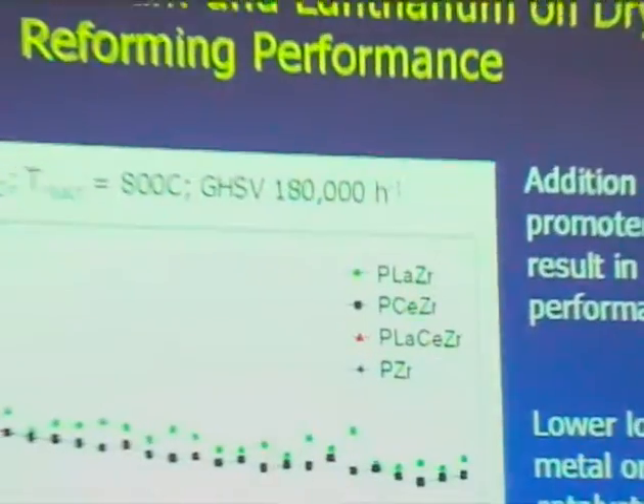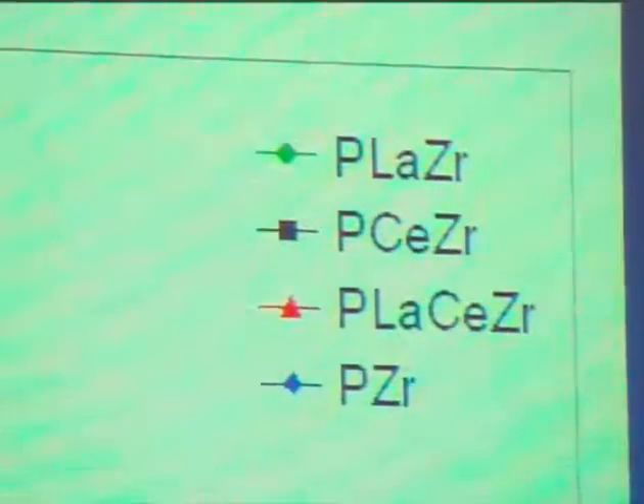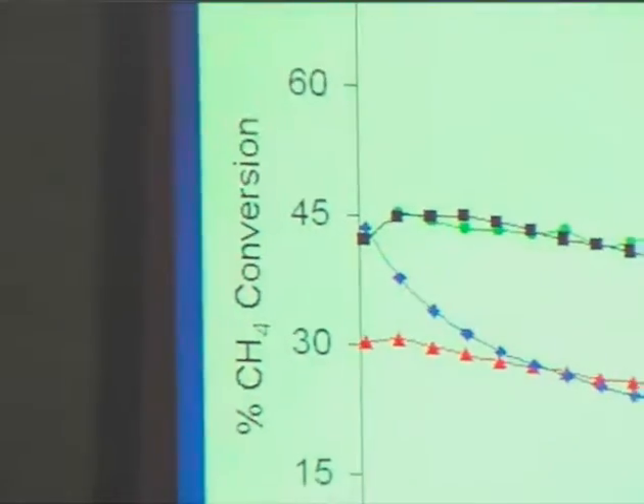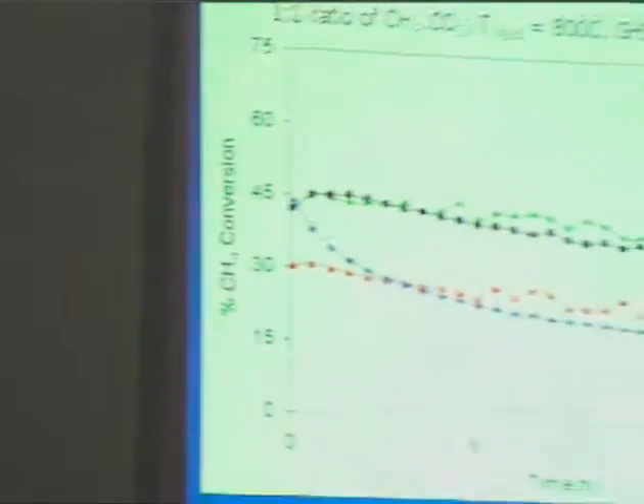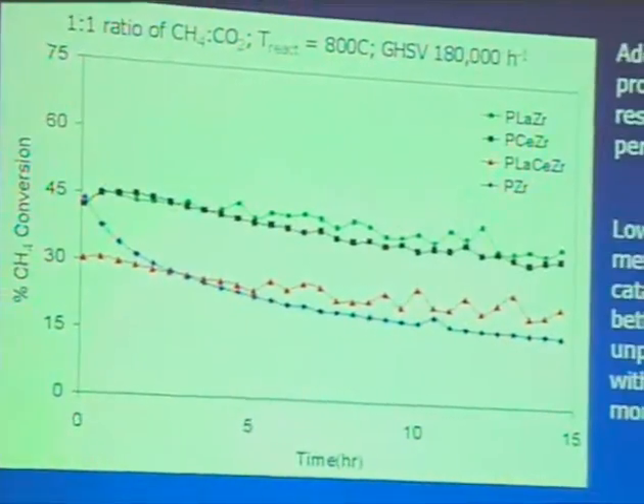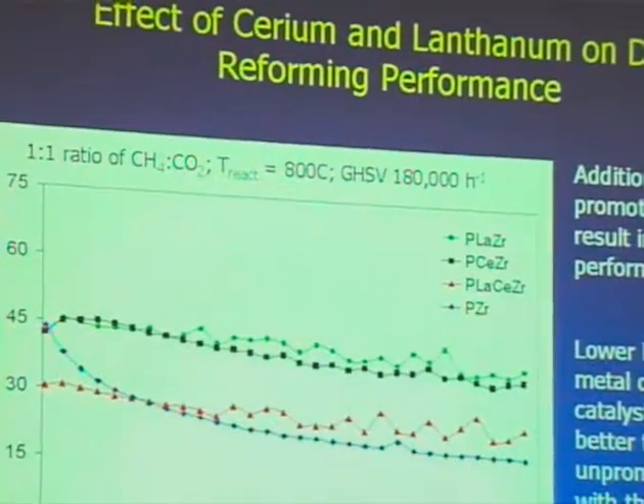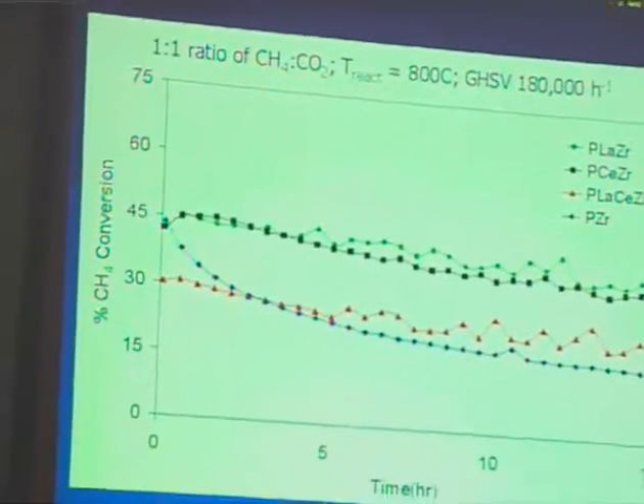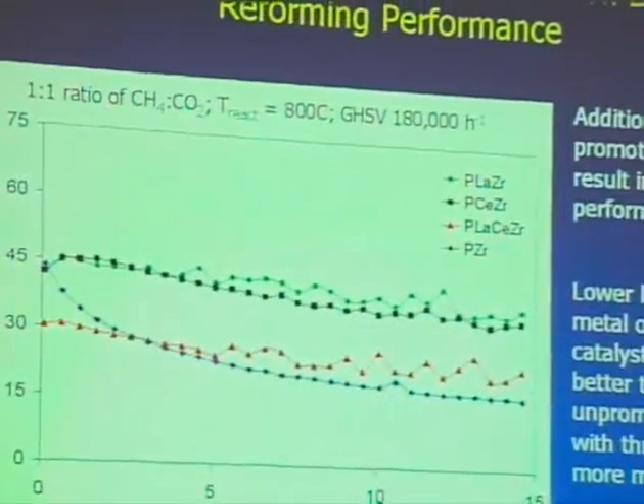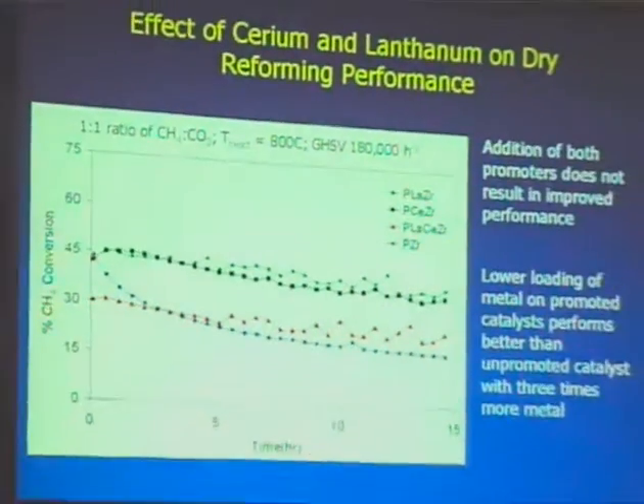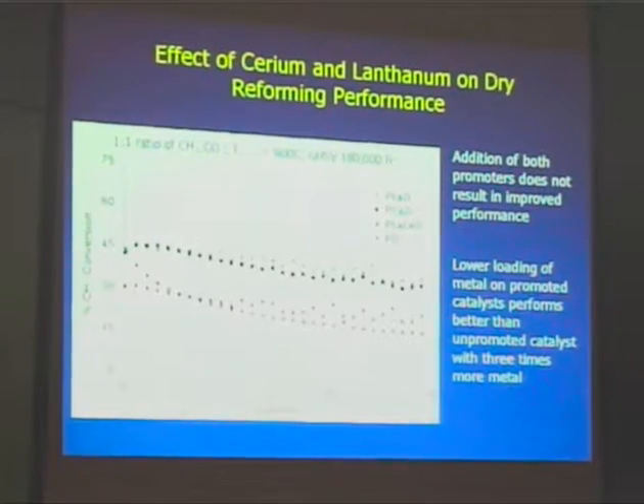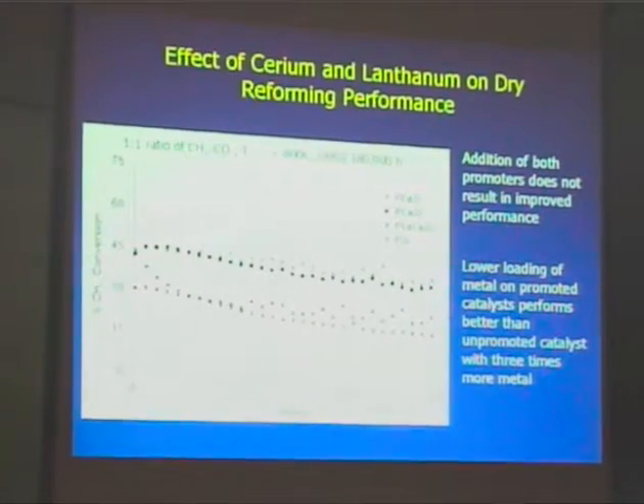If we look now at the effect of the ceria and lanthana on dry reforming performance, we see that the individually promoted materials, the materials with the lanthana by itself and the ceria by itself, have very high activity and minor deactivation over the course of a 15-hour experiment with a 1-to-1 ratio of methane to CO2 at high space velocity. When you compare that to the platinum zirconia, you can see here, this is the one with rapid deactivation, so there's a significant difference in those materials, even at a 1-to-1 methane to CO2 ratio.